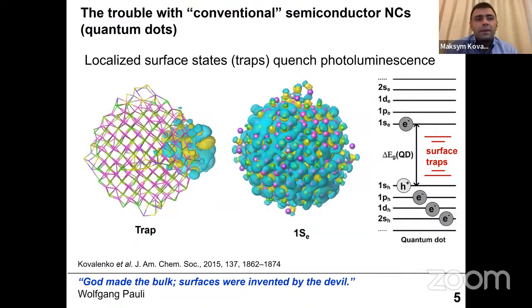Now, what was not so exciting from the beginning was to notice that the light emissive property of this quantum dot was not that great at all. And the problem back then was that quantum dots as produced do not exhibit bright luminescence. And luminescence, as you know, is a reversal of the absorption, right? So that the photo-generated electron-hole pair recombines back. And the big hope for these materials was that they will emit light with high luminescence quantum efficiency, and therefore they can be used as inorganic nano-sized light emitters. But they turned out to be very bad light emitters as produced.